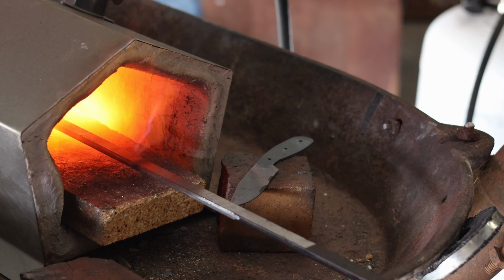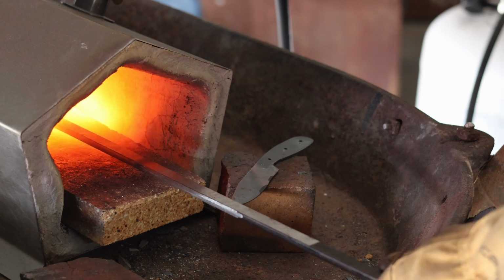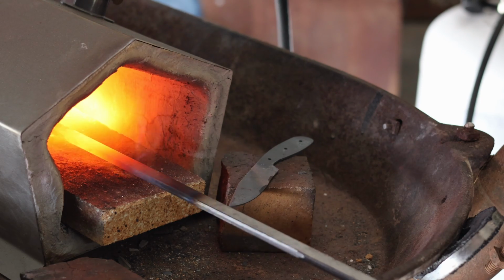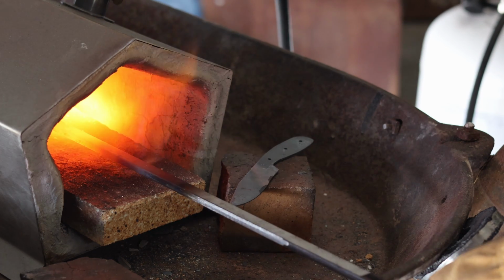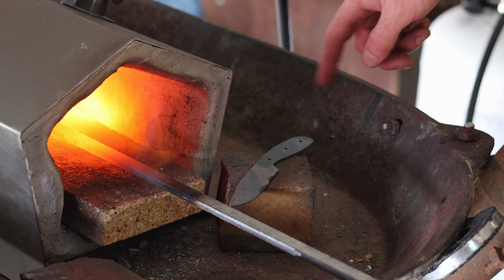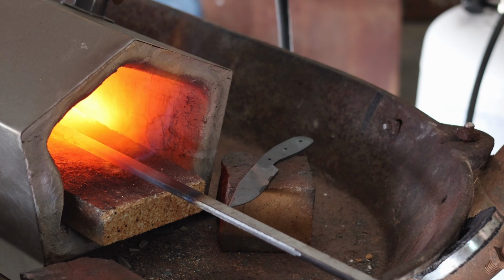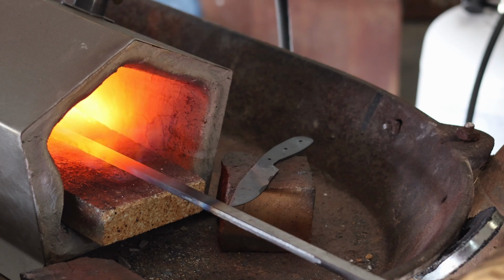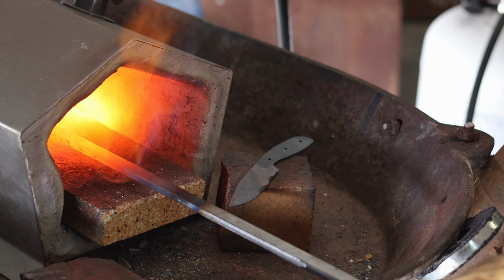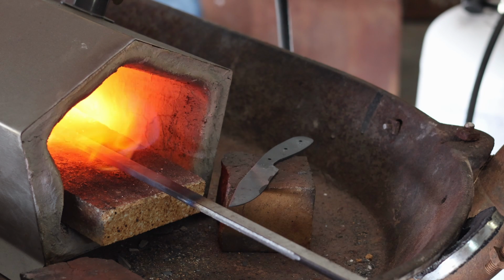Okay, so I'm just in the process of heating up my quench oil. I'm just getting a bar of mild steel up to an orange heat. I'm letting the knife warm slowly close to the mouth of the forge back to a reasonable temperature. The quench temperature for 1095 is about 1450 to 1475 degrees Fahrenheit. I'm going to take it to non-magnetic and then a little bit hotter. That's why I have a magnet here, and let it soak at that temperature for about 5 minutes.